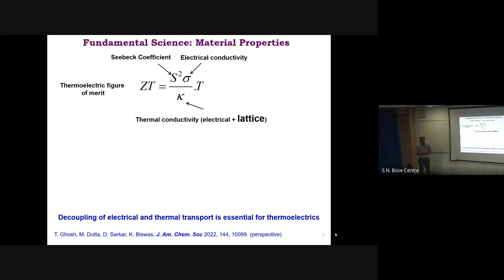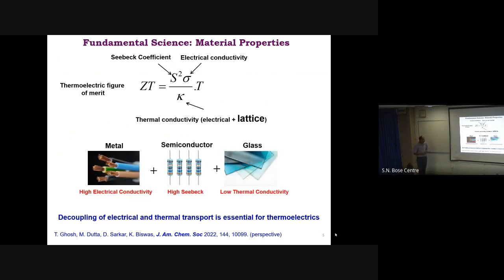As a solid state chemist, I look at the problem in a slightly different way. We need the property of a metal, which has high electrical conductivity, the property of a semiconductor, which has a high Seebeck coefficient, and the property of a glass, which has low thermal conductivity. So, can anyone synthesize a material with the properties of a metal, a glass, and a semiconductor in a single material? That is the grand challenge in this field.